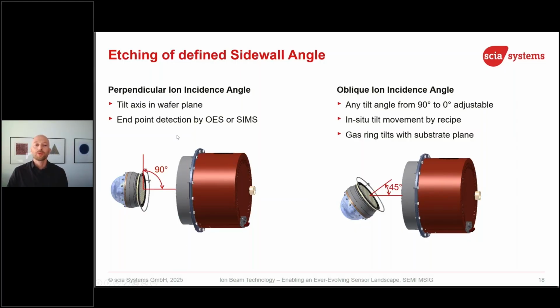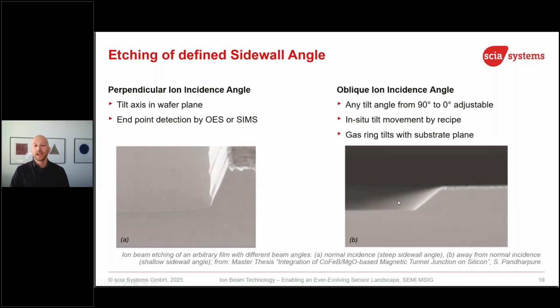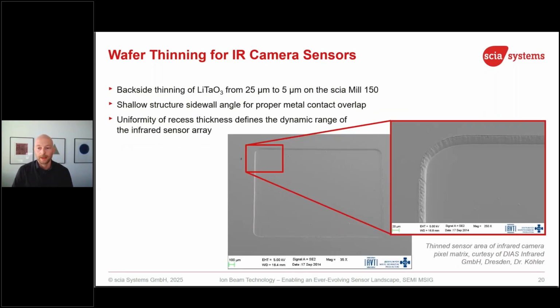So if we have 2 processes, one with a perpendicular angle of incidence for our ions and one with 45, and then we do the etching, we would see that the etching angle is different. So we can control the sidewall angle very nicely. And in the next example, that's actually needed, we don't want to have 90 degrees, because we have one customer doing infrared sensors.